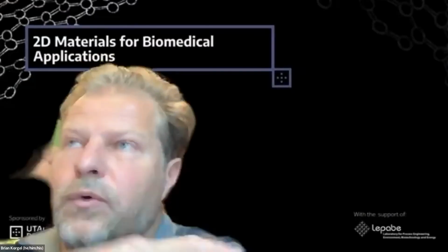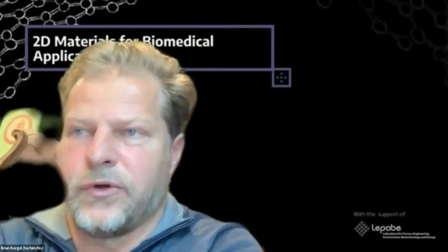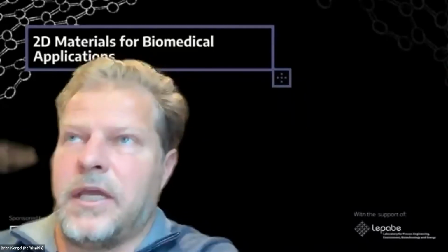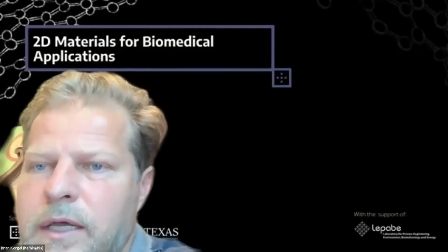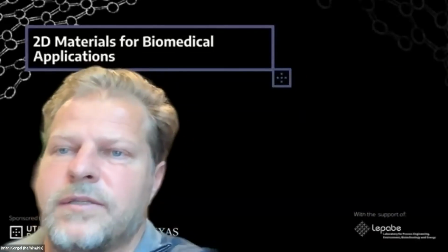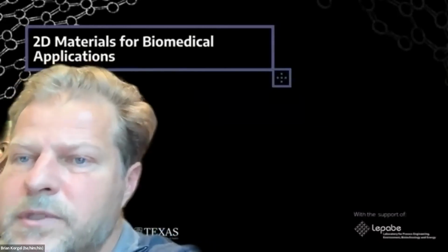Yeah, when you do the HCl, you get some hydrogenation. So some of the silicon is terminated by hydrogen, but also silicon atoms are terminated by hydroxyl groups. So in that HCl process, you do get that sort of oxidation. But within the bulk siloxene, the silicon's still relatively protected from oxygen exposure and water. And so you don't get this oxygen insertion into the silicon until you exfoliate, and then you have to be careful with the degradation of the material at that point.